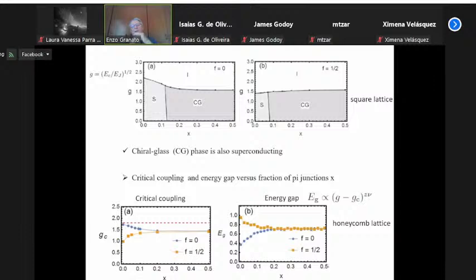So the phase diagram will be obtained by varying the doping, varying the concentration of impurity, as illustrated here for zero field and for f = 1/2. And there are three phases: superconducting, chiral glass, insulating phase. They are qualitatively the same, but again, the difference is that for a small disorder, for zero field, the critical coupling decreases before reaching a plateau, whereas for f = 1/2, it increases before reaching a plateau.